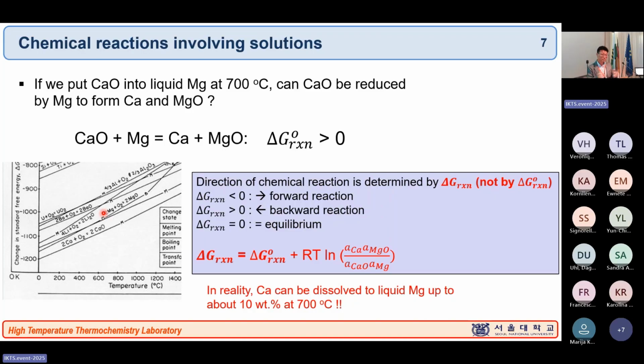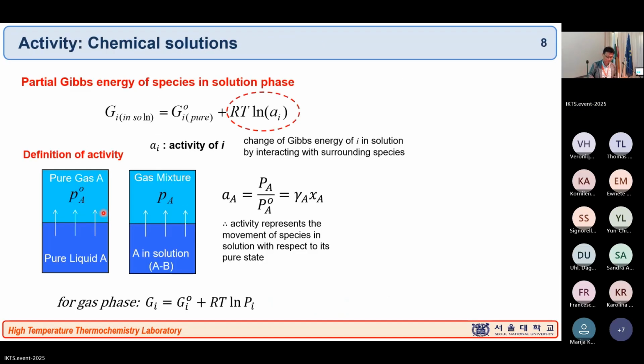And he made a patent, for the magnesium alloys and also as an additive for the aluminum alloys as well. And it's a huge patent. When this technology was first patented, and he introduced it on the academic side, at the conference, nobody believed it. The Ellingham diagram didn't say that. But this is the reason. You can actually do it.